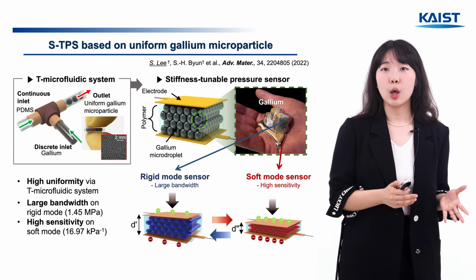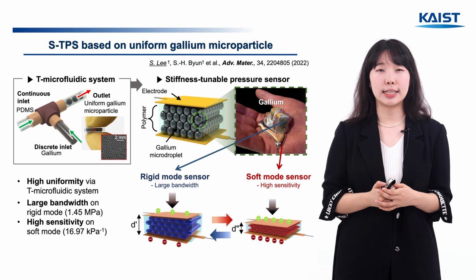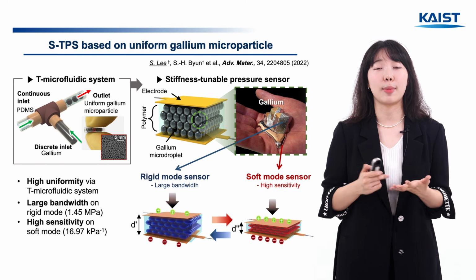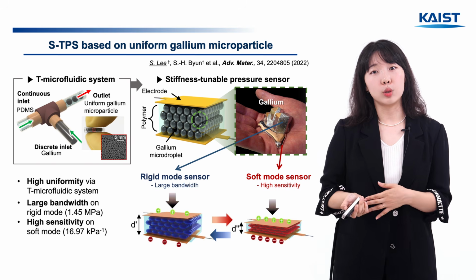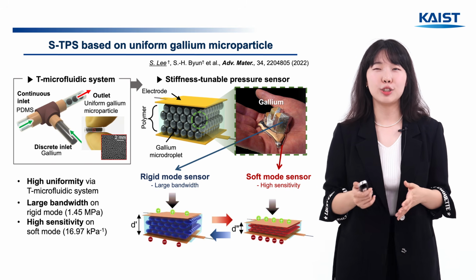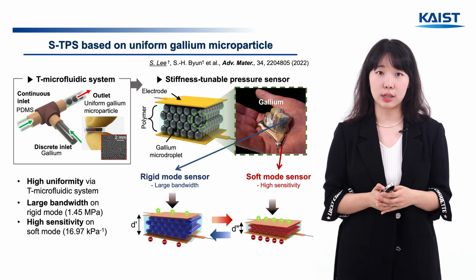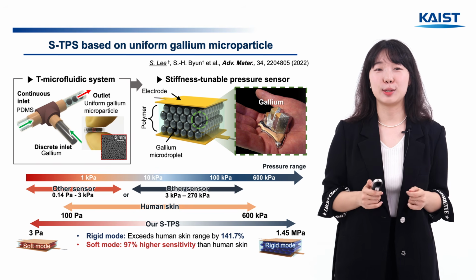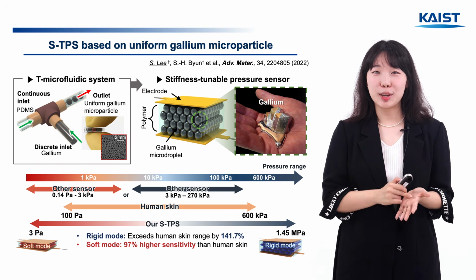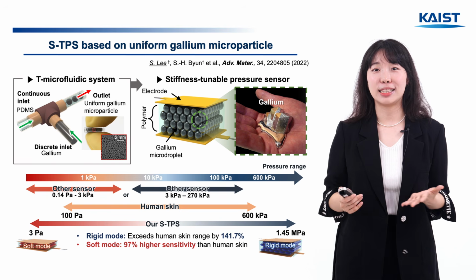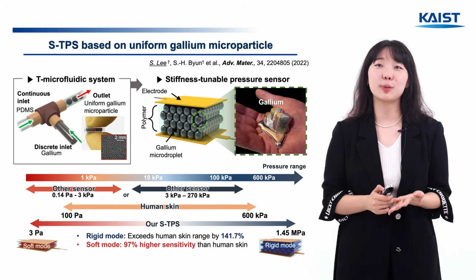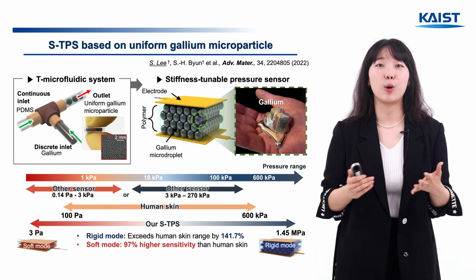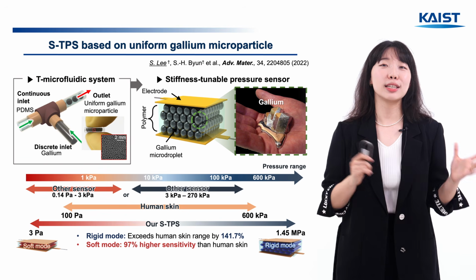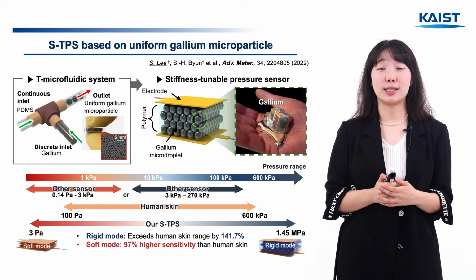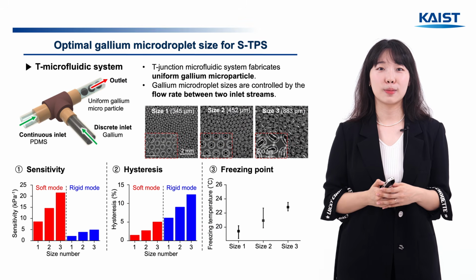In the rigid mode, where the gallium is frozen, it senses up to 1.45 megapascals. In soft mode, where the gallium is melted, it reaches a sensitivity down to 3 pascals. And these values represent a 141% improvement in sensing range and a 97% improvement in sensitivity over human skin. So across these two modes, the sensor surpasses what human skin can do.